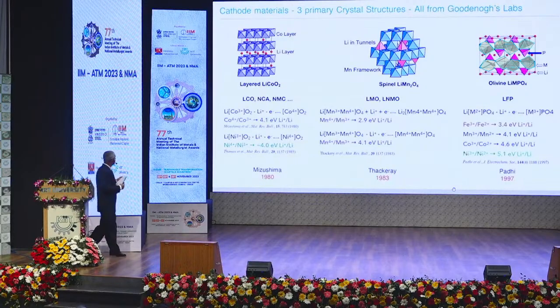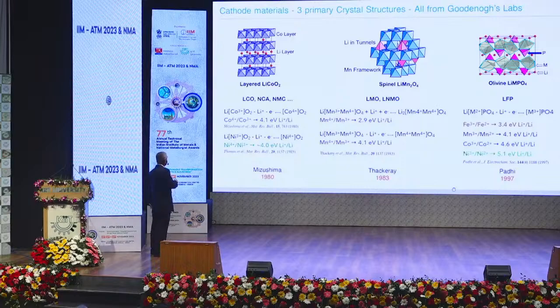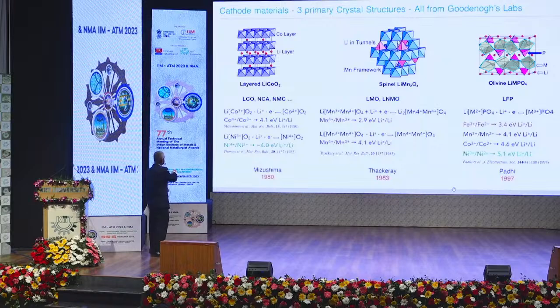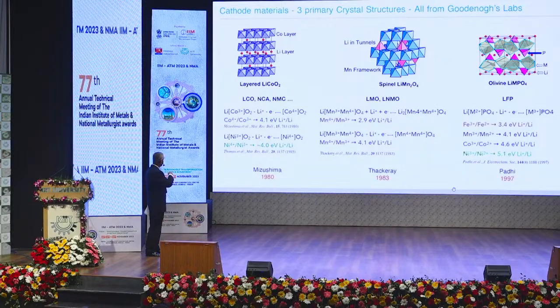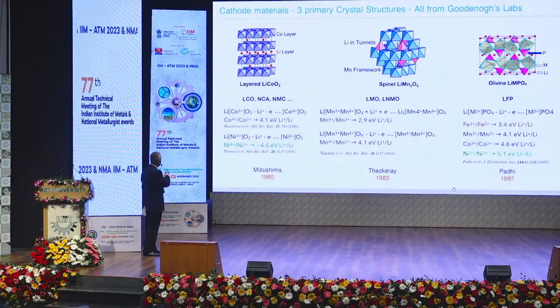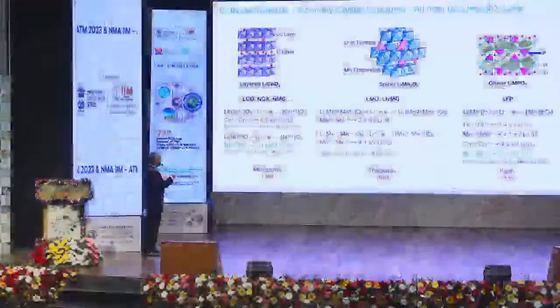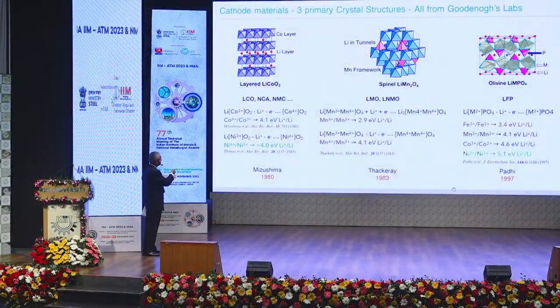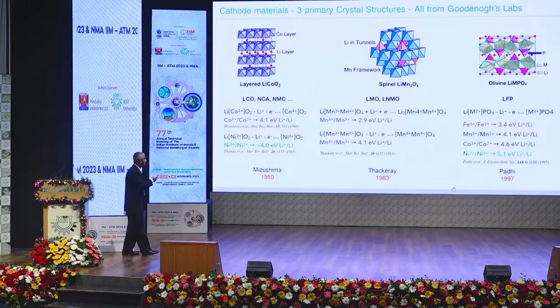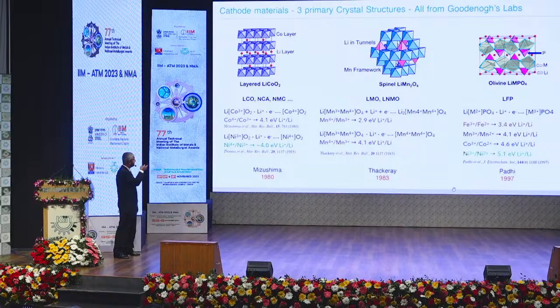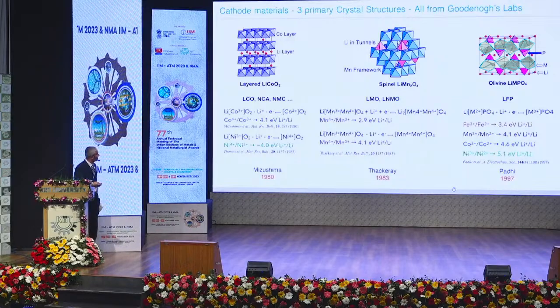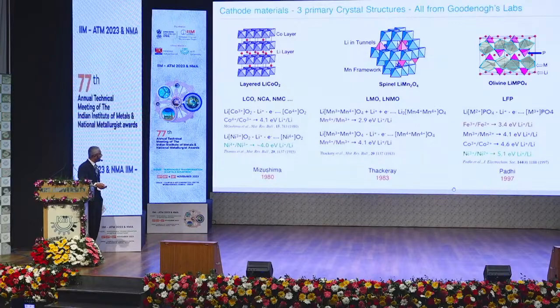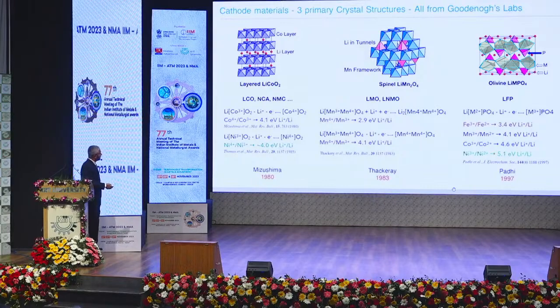So to summarize all these cathode materials, there is the lithium cobalt oxide structure with a layered structure, and we can make all these materials like LCO, nickel cobalt aluminum oxides, and nickel manganese cobalt oxides in the layered structure. They also identified in 1983 another material, spinel, which is an oxide framework that has three-dimensional channels for lithium ions. The manganese ions are located in the octahedrons, and the tetrahedrons contain lithium ions. So this material is very good, but still it had some performance problems that I will discuss.